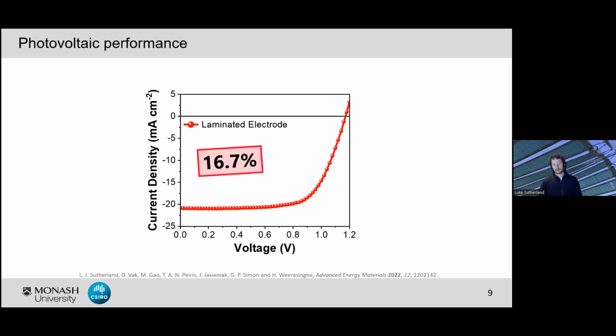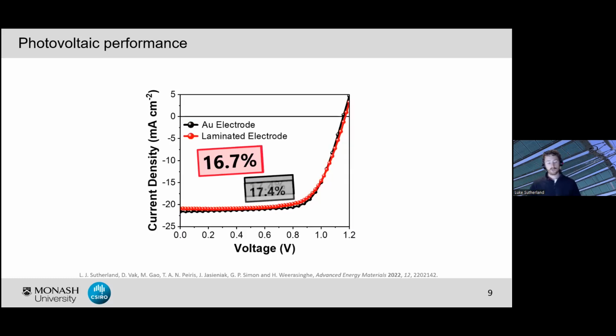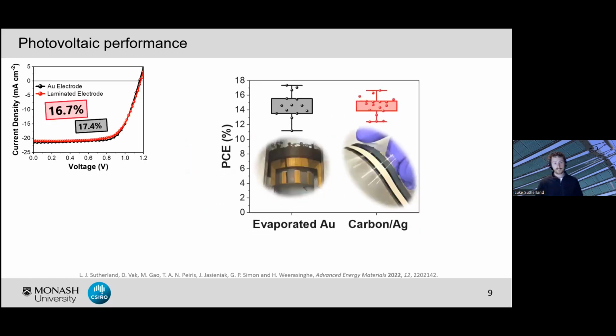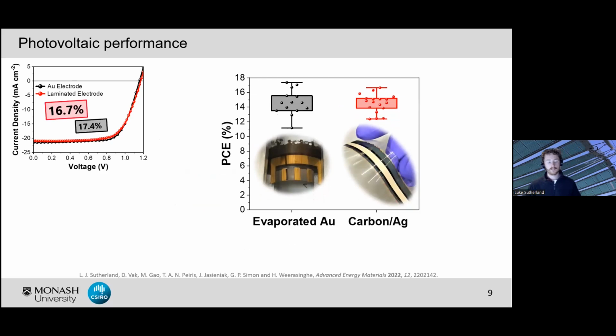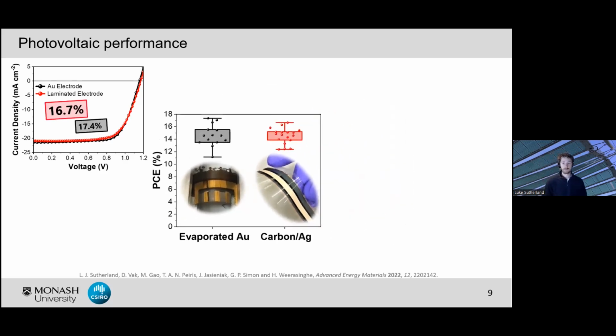But really, what we wanted to do was compare this to devices with evaporated gold electrodes. And so out of the same batch, exact same processing conditions, except with evaporated gold, we were able to achieve a maximum efficiency of 17.4%, which not only marked another record for an evaporated gold device, but really what I want to demonstrate here is the direct comparison between the device with our laminated electrode and those with the evaporated gold. This is even better seen once we look at the performance distribution of all the devices in our batch, where despite our evaporated gold exhibiting that exceptional performance for a number of cells there, overall, we get great comparison between the two device types.